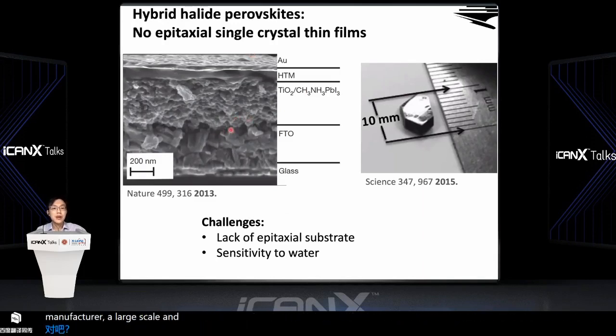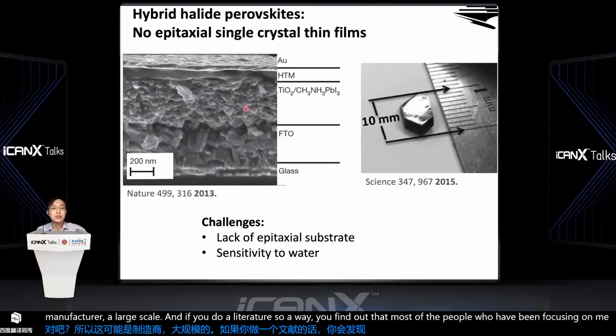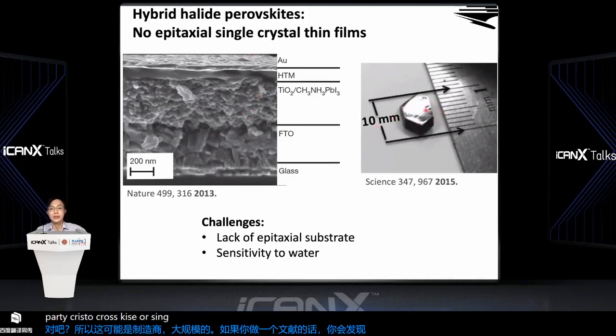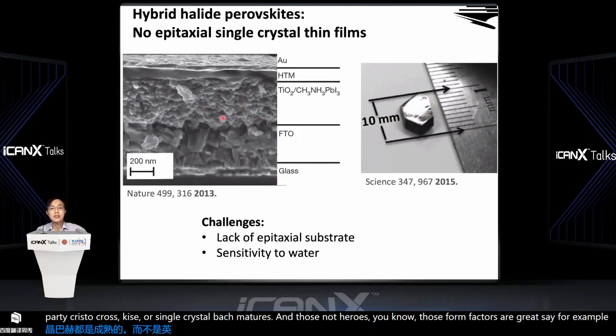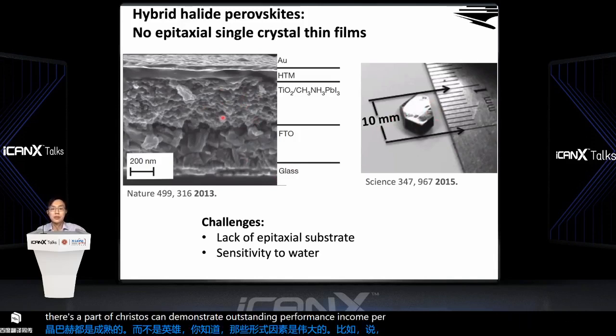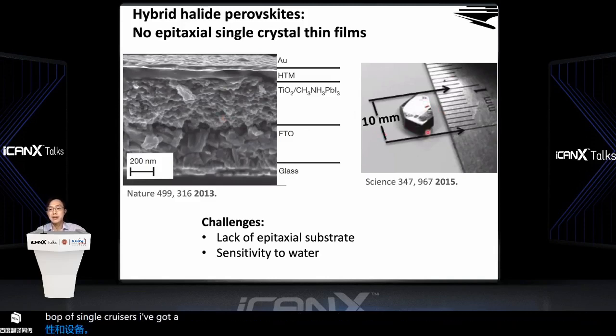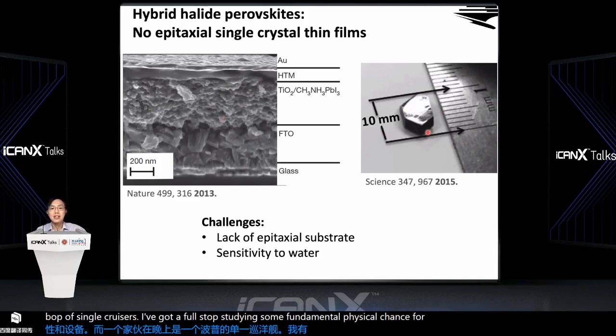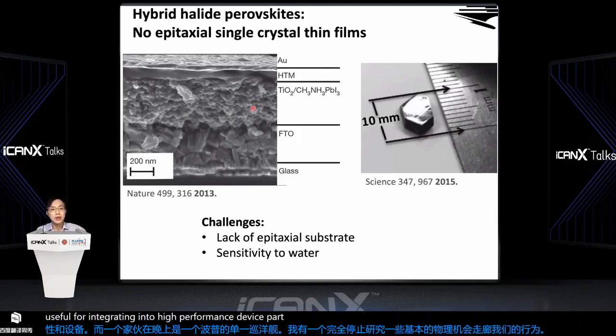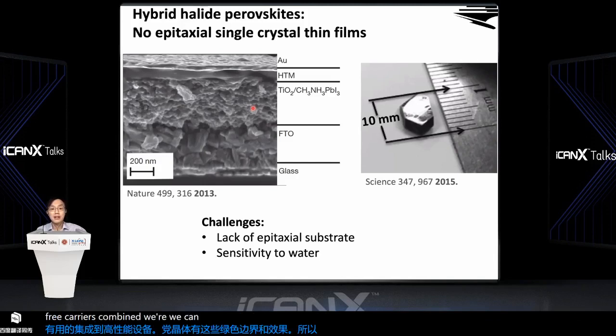And if you do a literature survey, you'll find out that most people have been focusing on either polycrystal perovskites or single crystal bulk materials. And those form factors are great. For example, these polycrystals can demonstrate outstanding performance in comparison to those silicon and gallium arsenide devices. These bulk single crystals are good for studying some fundamental physical transport behaviors, but they are hardly useful for integrating into high performance devices. Polycrystals have those grain boundaries and defects. So those free carriers will recombine, will annihilate before they get collected, right? So the performance will degrade.